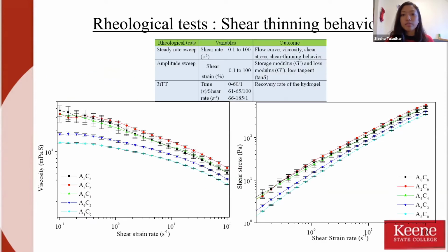So this is the first rheological test that we did. It is called the flow curve. And this is the result of the flow curve that we did for the concentrations, the compositions that we made. For this experiment, we made sure that the shear rate was 0.1 to 100. The shear strain for the amplitude sweep test was 0.1 to 100%.